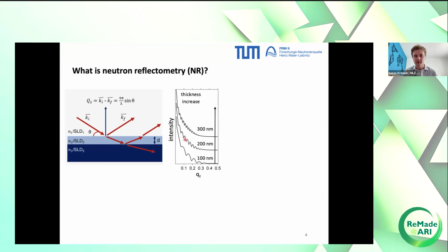And there are 2 important features. The first feature, here it's barely visible, apologies for this, but this is the critical edge. So this is at very low Q values. You have a certain region where you have total reflection. So there the neutron is not able to penetrate the film, and all of the neutrons get reflected. This is then called total reflection. And then at some QZ value, neutrons penetrate the film, and then you get this very characteristic shape with these fringes here. They are called Kiessig fringes. And they depend strongly, for example, on the film thickness. So if you increase the thickness, these fringes move closer together. And this is how you get information about the film thickness, for example.